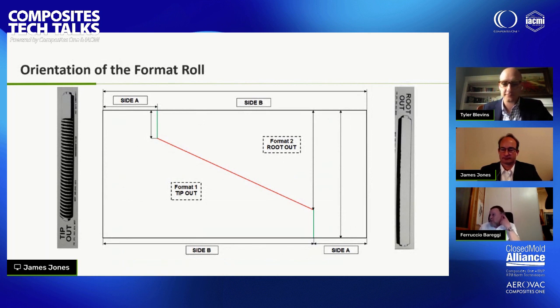So if you want to go back to the formats, the formats always come from a lay flat tube roll onto which we do the nesting of 2 formats of the same dimension. Consequently, we will always have 50% of the formats that are wound up tip to root and 50% that are wound up root to tip.